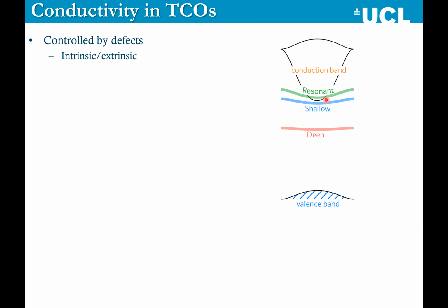And we normally define shallow as being less than 0.03 of an electron volt, because at that energy range, you're about kT. So you will have appreciable conduction at room temperature. And then resonant defects are when the donor states actually sit high above the conduction band minimum, meaning that the electrons are injected directly into the conduction band. This is ideally what we want in a good transparent conducting material.